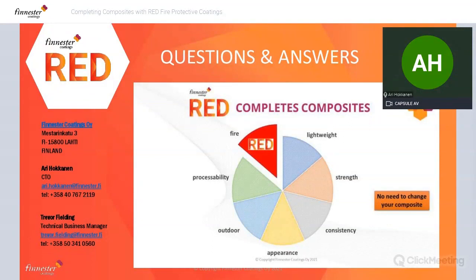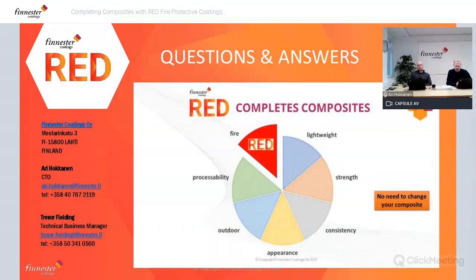One further question here, can this product reduce the blistering effect on colored coating of carbon fiber? Blistering effect, it doesn't blister. So I maybe didn't fully understand. No, I think it's to do with the adhesion and how things happen with carbon fiber. So have we seen? We've worked with carbon fiber. Yeah, we've got good results. Or is it osmosis? Yeah. So it has very good osmosis resistance, and the Red technology works beautifully. It's a high performance coating if you don't care about fire at all. So it's still a very nicely performing coating, but it has that added ceramification effect when fire is involved.